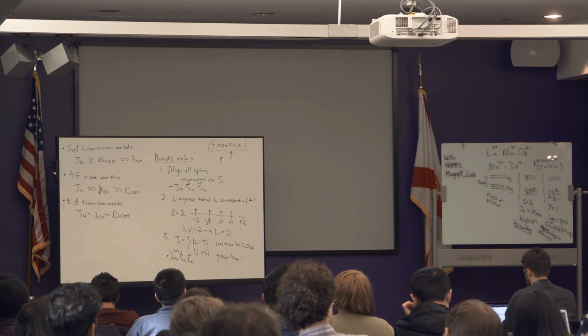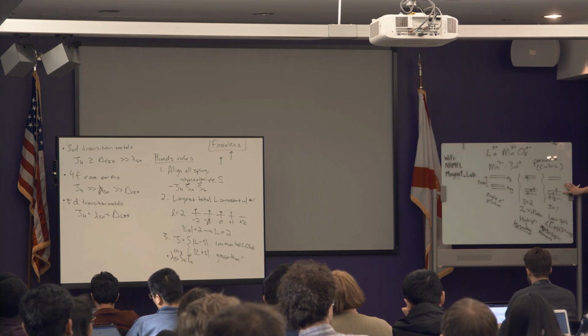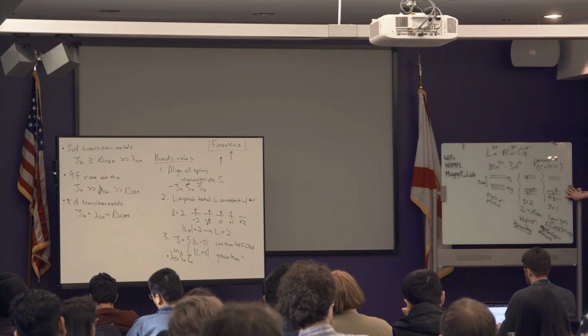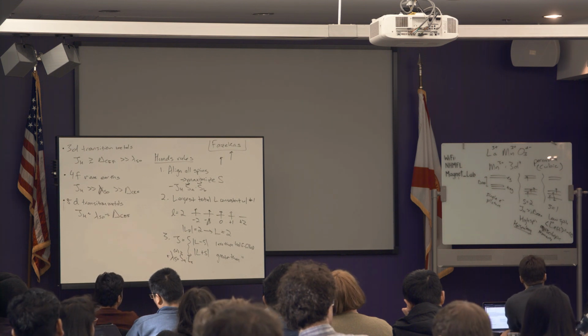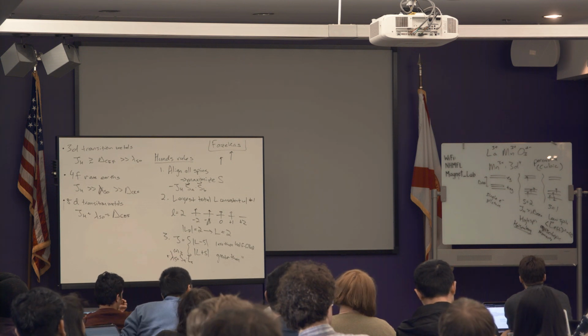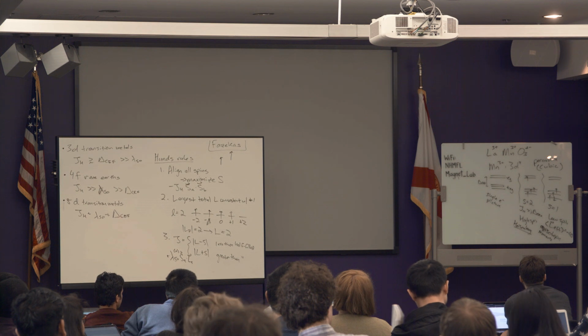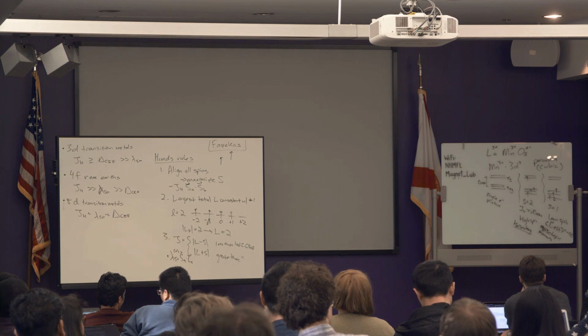And just so you know, symmetry tells you what your possibilities are. It doesn't tell you what order they're in. So here I put my symmetry. The cubic symmetry just tells me I have a T2g and an Eg. It doesn't tell me what order they're in. You can guess that by looking at the particular structure. That sometimes works. It works really well for transition metals. It doesn't work really well for rare earth ions. So usually what you'll do is actually you can measure this.